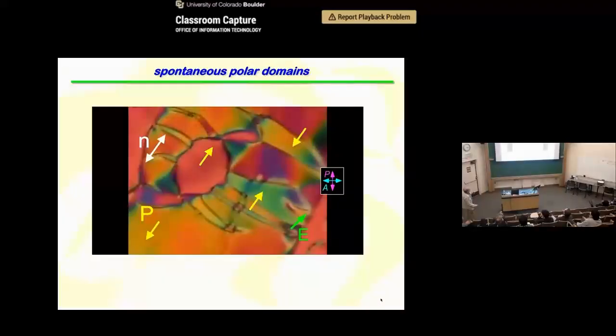Okay, so this is evidence that this lower temperature phase has a ferroelectric polarization that's coupling to the field, and that the sign of this polarization is opposite. So these two domains are domains of opposite ferroelectric polarization. The polarization appeared spontaneously upon cooling into this phase and formed domains, and these domains could be manipulated with an electric field. So these are the essential elements of ferroelectricity.